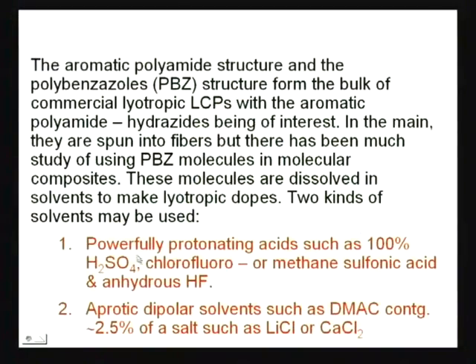Dope means a solution is called a dope. If you put something in a highly viscous system, it is called dope. Solution of a solute in a solvent is called a dope. Two kinds of solvents may be used. Look at the solvent: concentrated sulfuric acid, or chlorosulfonic or methane sulfonic acid, or anhydrous hydrofluoric acid, hydrogen fluoride. You see, very critical solvents, very strong harsh solvents.